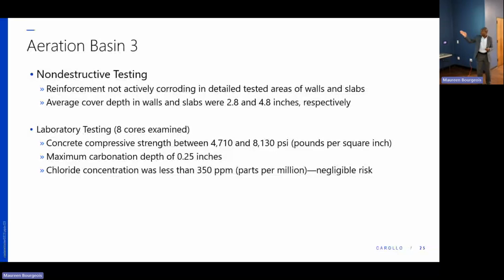Then with the laboratory testing, we did 8 cores. We tested 8 cores specifically for the various lab testing that we talked about earlier. We start with compressive strength. We talked about the load that the concrete needs to see before it crushes. And so that load here for this particular structure is in the 4,700 to 8,000 pounds per square inch range. The minimum we want for this structure documented on the design drawings is 4,000. We exceed that, so the structure has structural capacity to hold.